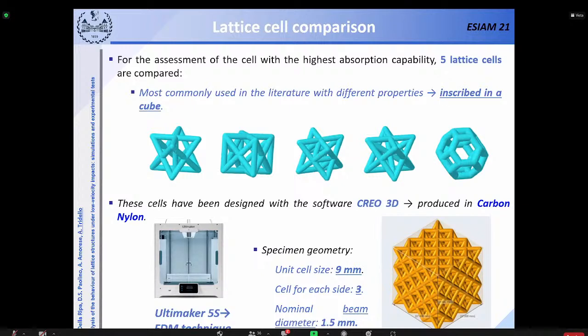And even with such a small specimen, the computational time required with this very simplified model was about 10 minutes. We also tried to run a 3D elements model, and it took more than 3 hours. Obviously, it depends on the machine that you are using, but with a commercial laptop, these were the computational times. But by dimension, I mainly meant the tensile.